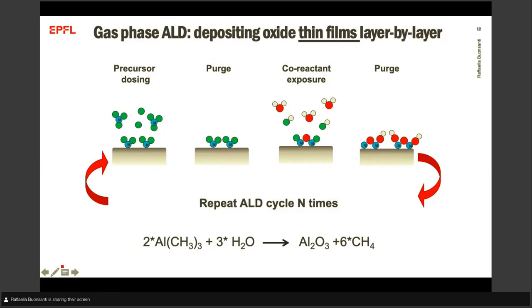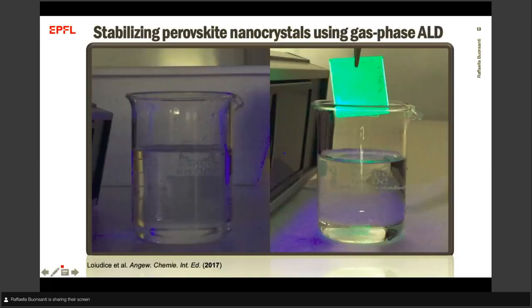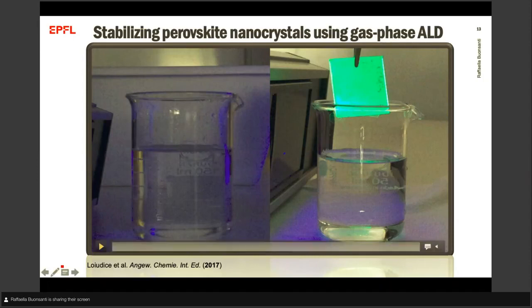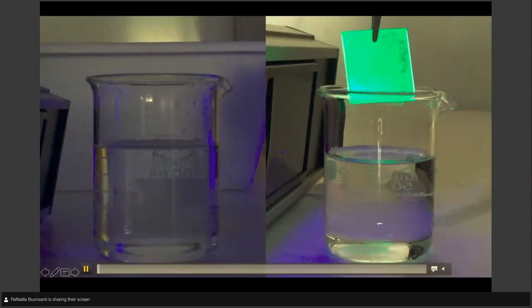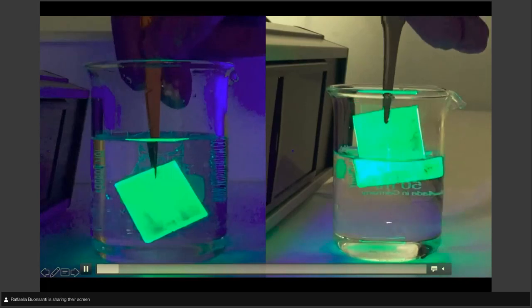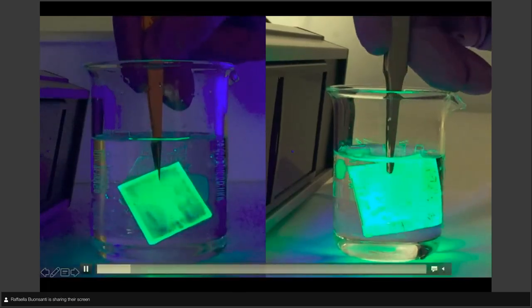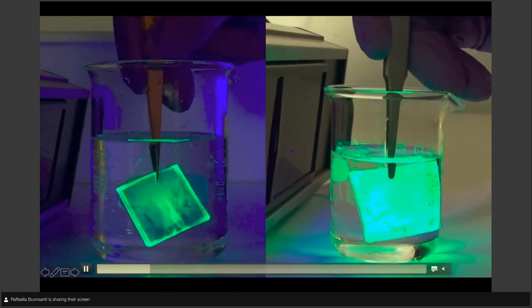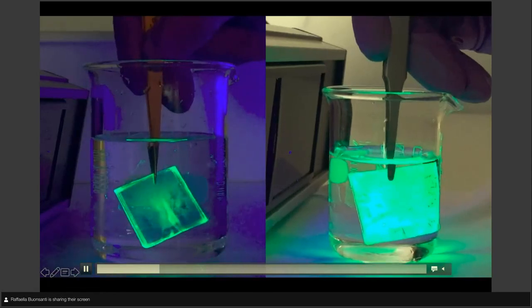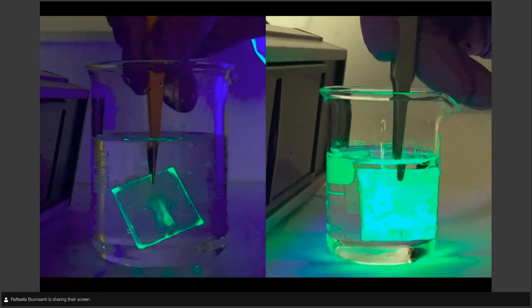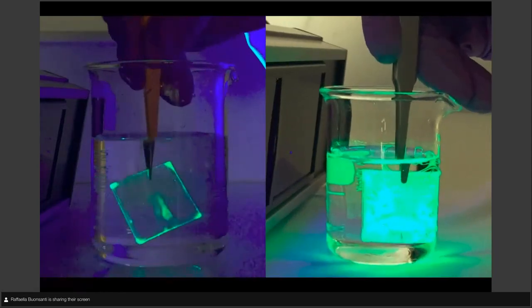You form the first layer of metal oxide, and then you can repeat the cycle in order to tune the thickness of this metal oxide. So we adjusted the process to fit with the perovskite nanocrystals, and this is work of my postdoc Anna. You can notice on the left a film of perovskite nanocrystals non-protected, which is dissolving in water, and on the right, a film of perovskite nanocrystals that has the alumina layer on top. So at least it can stay in water for some time.